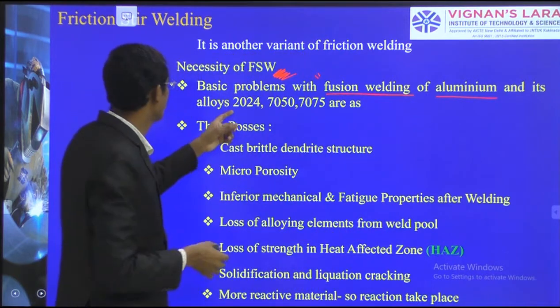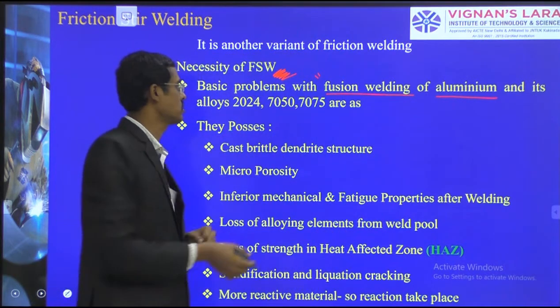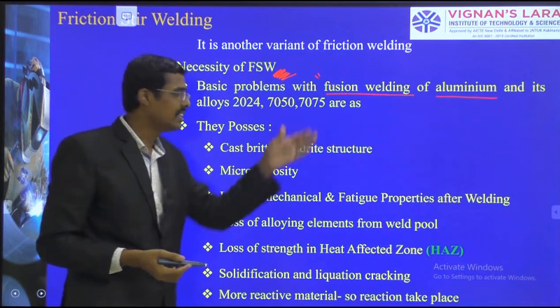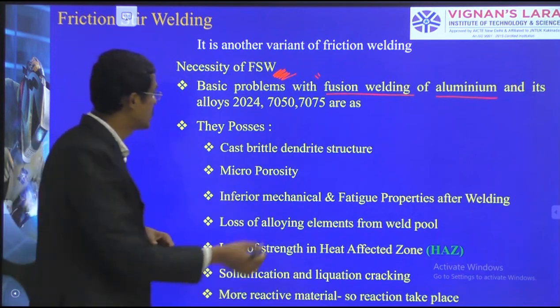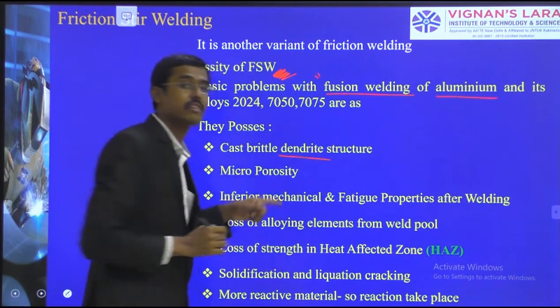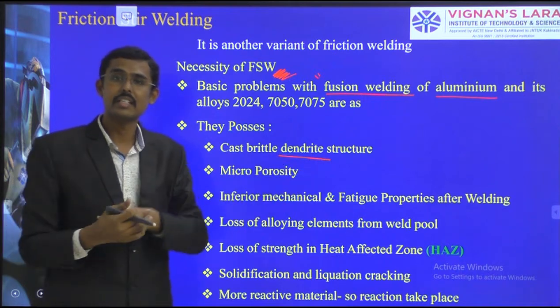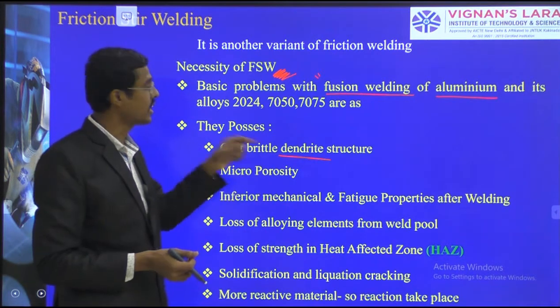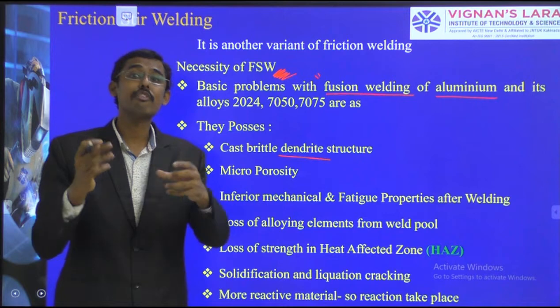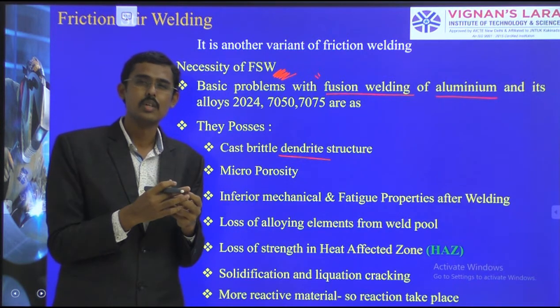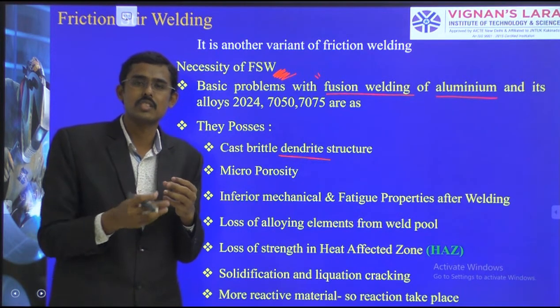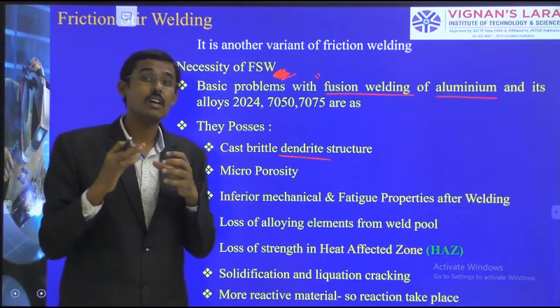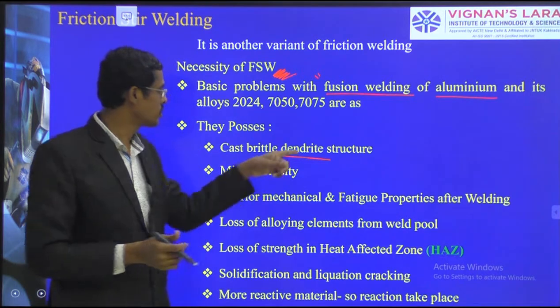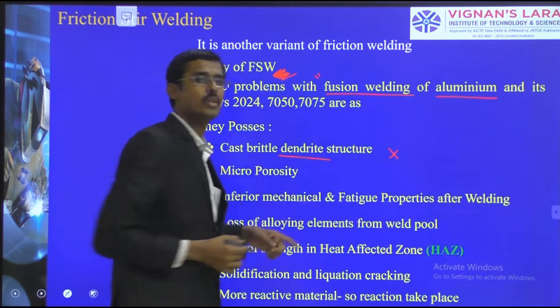In fusion welding of aluminium, some grades like 2024, 7050 and 7075 have the ability to generate dendrite structures. We have seen this in metallurgy in solidification. A dendrite is a tree-like structure which is sharp, and the sharp points generate cracks, which is not good for the material. That should be avoided. But what to do here?